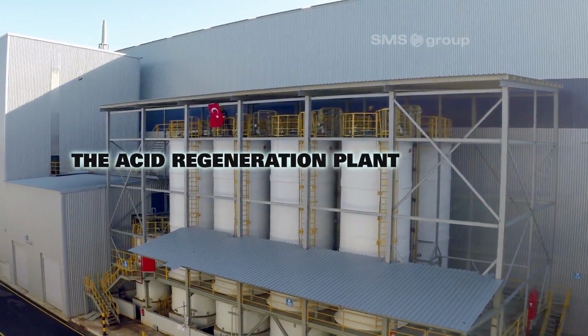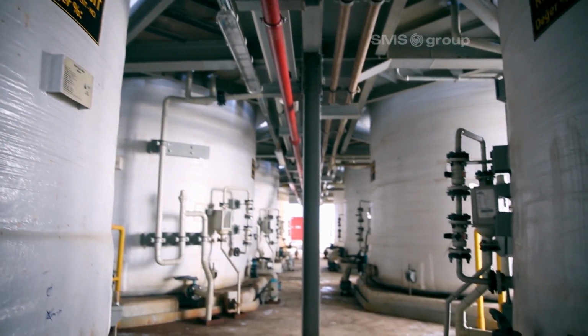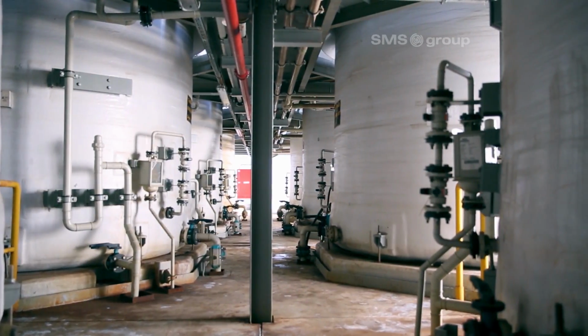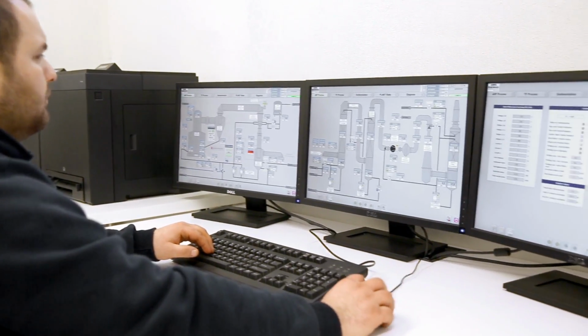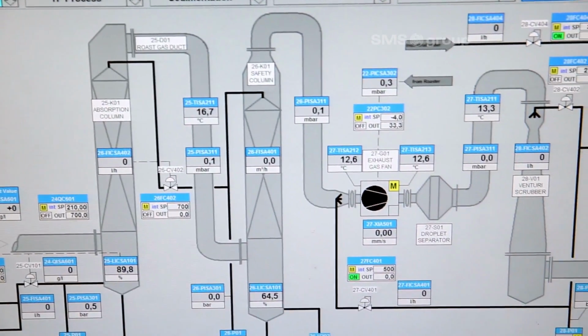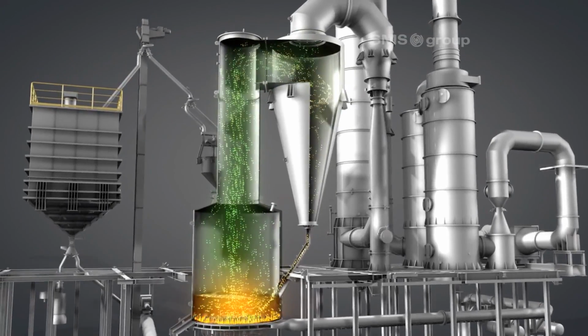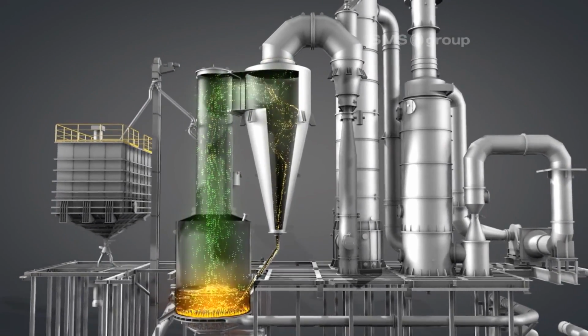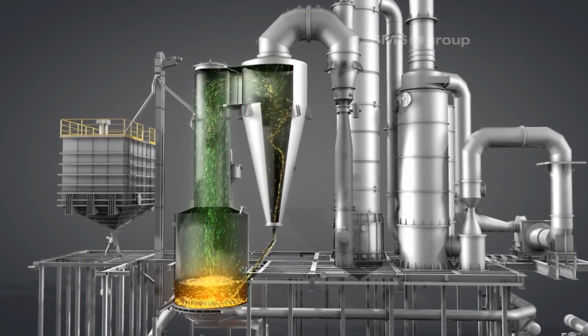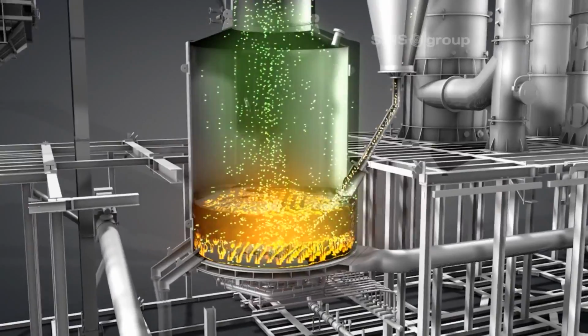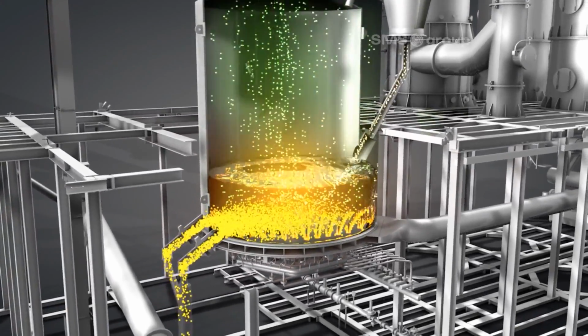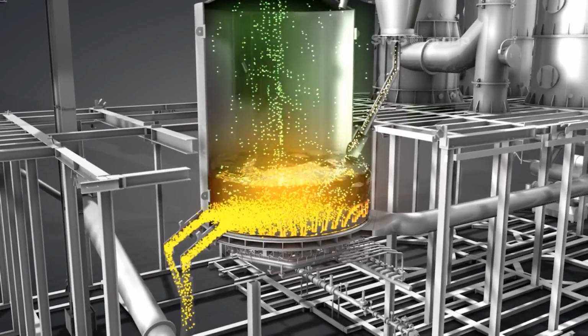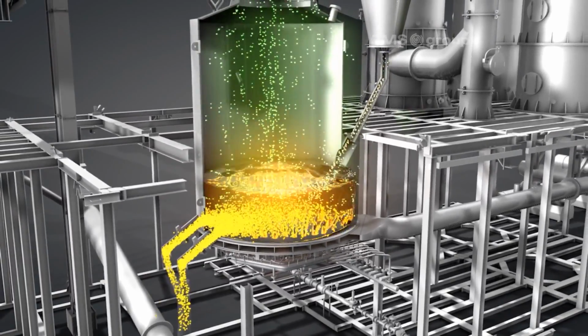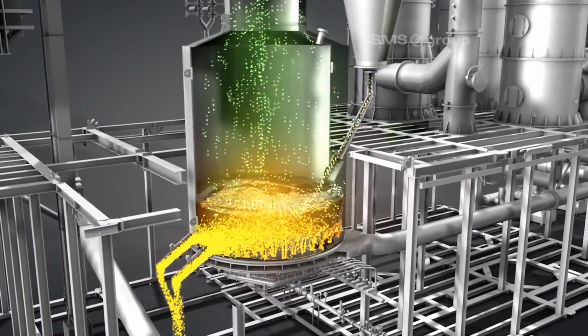The used iron-enriched hydrogen chloride is recycled in the acid treatment plant from SMS at a rate of 1,700 liters per hour. The whole acid volume of the pickling line is covered by this. In the fluidized bed furnace, the used acid and the rinsing water are separated into their individual chemical components at around 900 degrees Celsius. One constituent is iron oxide granulate, which is formed from the spent acid. It is withdrawn continuously from the bottom and can be reused as a recycled resource.